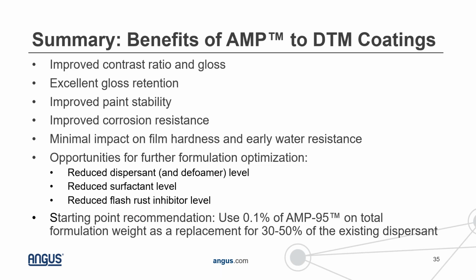So in summary of the benefits that we're seeing with the use of AMP in these waterborne direct to metal coating formulations, we see improvements to contrast ratio and gloss, very good gloss retention. We also see improvements to paint stability and corrosion resistance. And at the same time, fairly minimal impacts on other film properties, such as film hardness or early water resistance. And this is really all coming from getting a better quality pigment dispersion using AMP as a codispersant. These materials are very strongly adsorbed to pigment particle surfaces, and they can really do a lot to help improve a lot of the properties of these formulations.